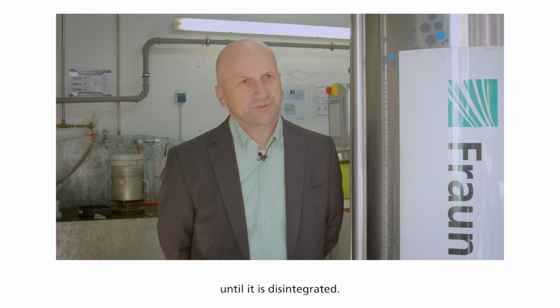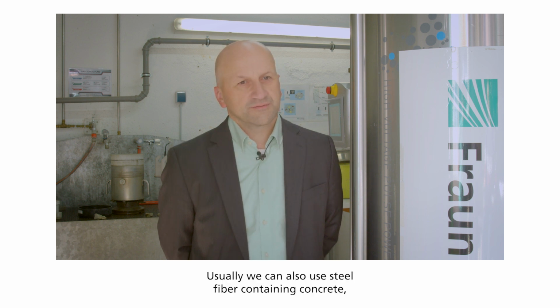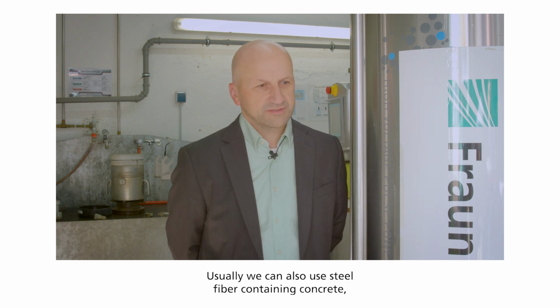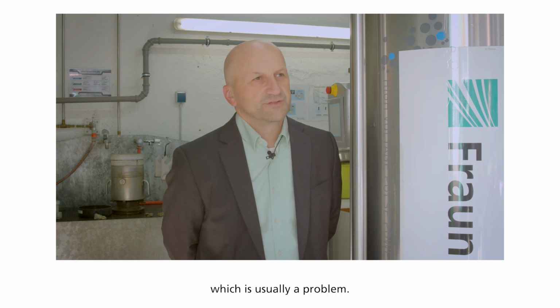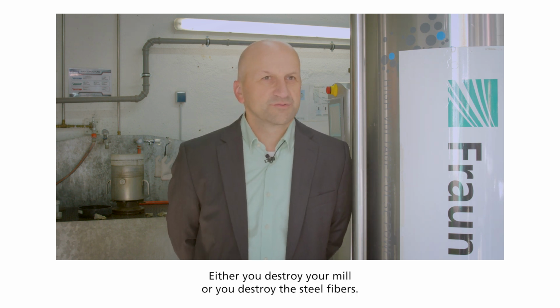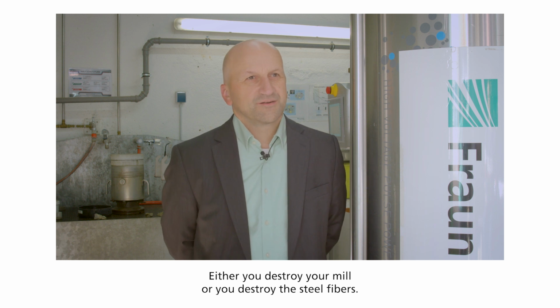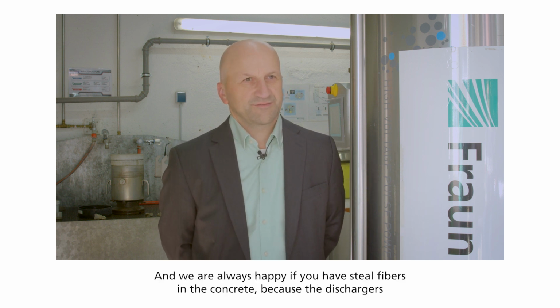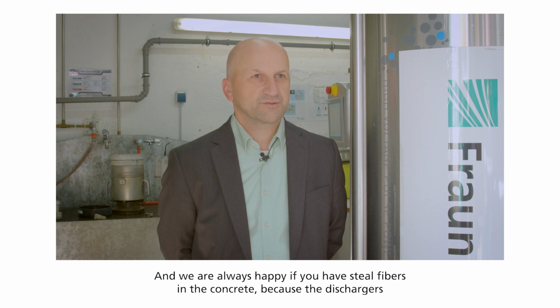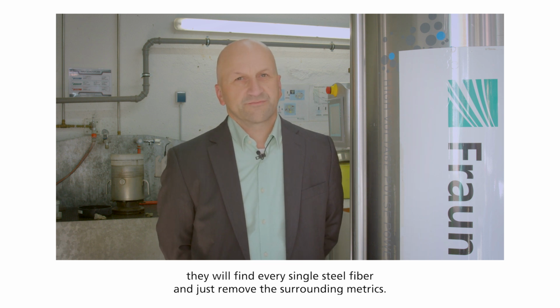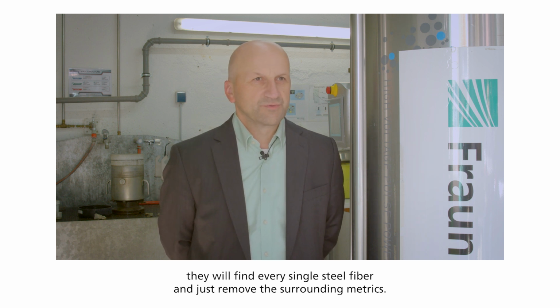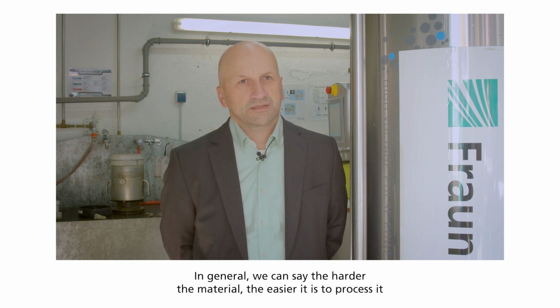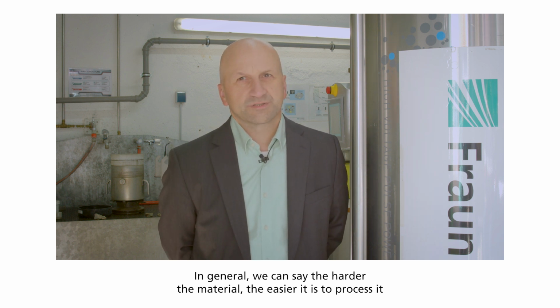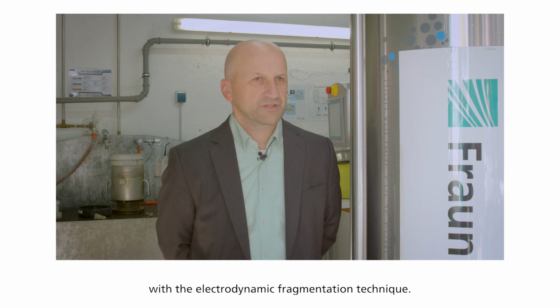it's disintegrated. And we can also use steel fiber containing concrete, which is usually a problem. Either you destroy your mill or you destroy the steel fibers. And we're always happy if we have steel fibers in the concrete, because the discharges will find every single steel fiber and just remove the surrounding matrix. In general, we can say the harder a material, the easier it is to process it with the electrodynamic fragmentation technique.